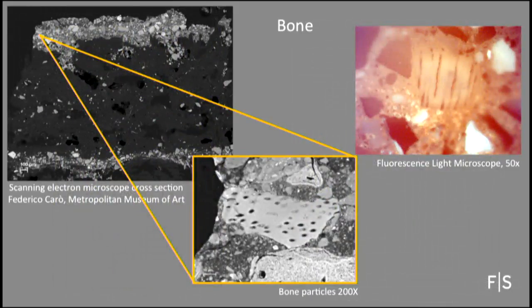When exploring the components of the lacquer, the most prevalent inclusion in all five sculptures is ground, partially burnt bone. It's clearly used as a filler to bulk up the lacquer, creating a dough-like paste that made it much easier to apply to vertical surfaces. Bone powder particles are non-absorbent, lightweight, and non-reactive to the very acidic lacquer. The bone particles are visible using microscopy, and their identification was confirmed by EDS in a scanning electron microscope. So what kind of bone was used in these sculptures?